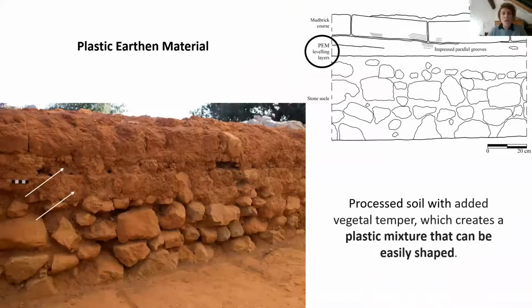The stone socle is generally closely associated with a 4 to 12 centimeter thick leveling layer of plastic earthen building material, the PEM, which is made of sediments with added vegetal temper, which creates a plastic mixture which can be easily shaped. The top of this PEM layer is carefully flattened in order to support the upper courses of mudbricks, and in several walls, stones of small dimensions, 5 to 10 centimeters, are stuck into the PEM layer in order to function as stone wedges and to increase the stability of the socle.